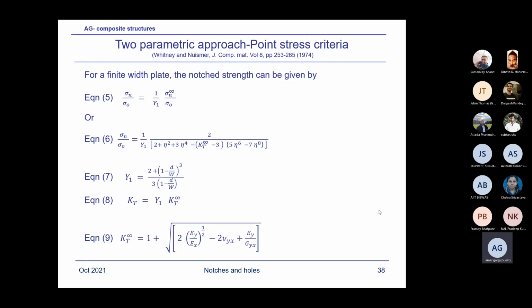About the delamination, just to know, sir, we cannot use this in the aircraft industries. Normally, the usual method is without considering the delamination growth, only as an approach. Only to have a reference on that. That's a complex phenomenon. There are methods available where delamination growth has been considered in some cases, but I would like to have a caution on that. It is not for proof. Sometimes the crack could jump the delamination, but yes, delamination theories have been developed in order to predict the delamination growth, similar to the metals.